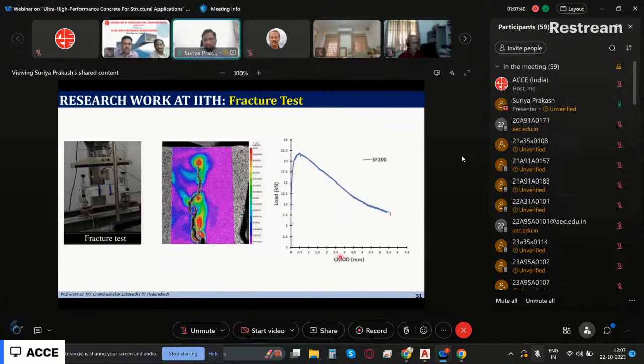And you see load, this is CMOD. CMOD stands for crack mouth opening displacement. That means at the mouth of this notch, we put a sensor and we try to see how much this crack mouth is open. And you see here, even after a significant crack, first of all, it took a very high load of 22.5 kilonewton. And even after that cracking, the crack propagation is slower and the strength is not dropping very suddenly. It is dropping very, very slowly.